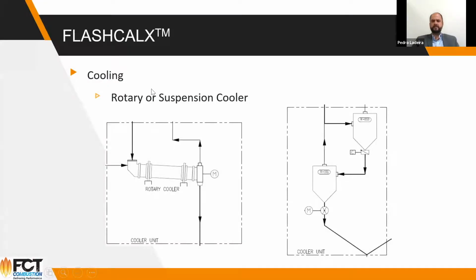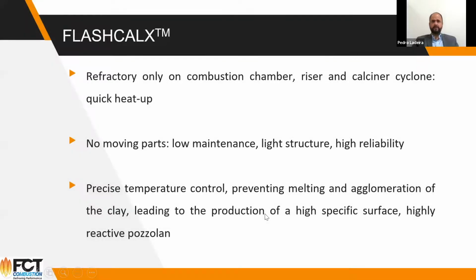And cooling, we have different setups as well. We have a suspension cooler. We can have a rotary cooler, again, depending on the feedstock and what the targets for the process are. The good thing about the flash calcination is that it has virtually no refractory, only on the combustion chamber, riser and calciner itself. So it implies a very quick heat up, while in a regular rotary kiln you take about 24 hours to heat up. In this case, you can go for 2 hours to heat up the system up to speed.